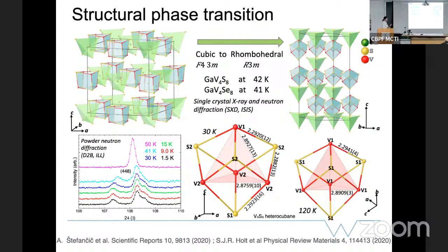Now, in this structure, you look at them as being made up of two different types of structural units. One of them being the vanadium 4 sulfur 4 heterocubane, and the other being the gallium vanadium 4 tetrahedra. So all the distortion that takes place as a result of the structural transition resides within these two units. This is the vanadium 4 sulfur 4 heterocubane, and you see the bond distances marked above the transition and below the transition, and you see the distortion in them.